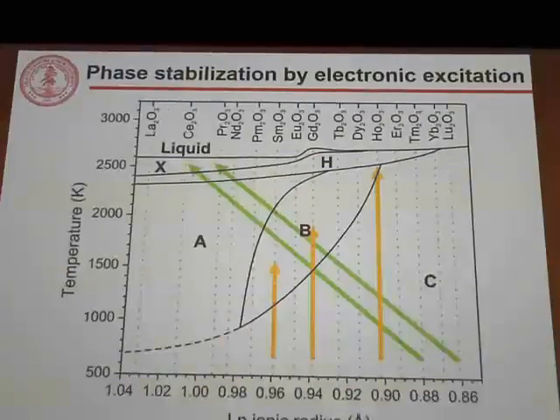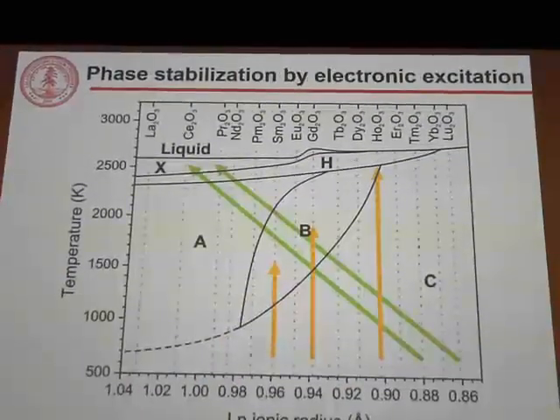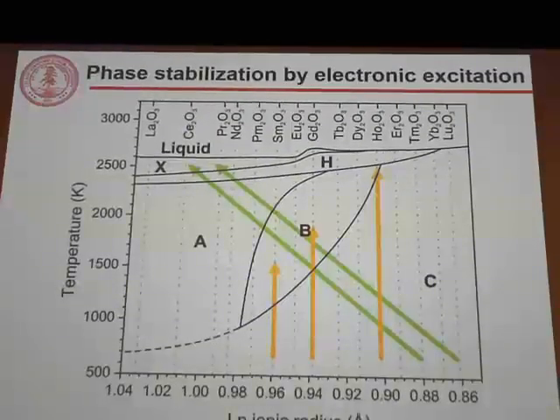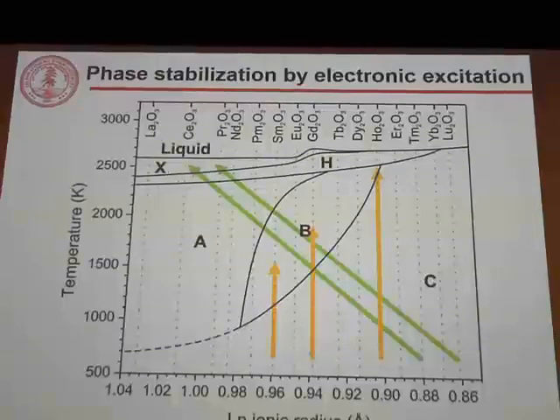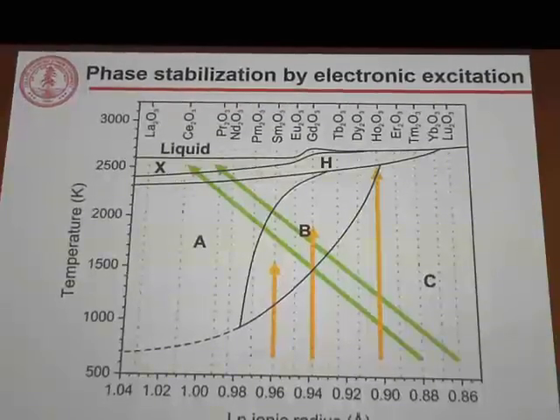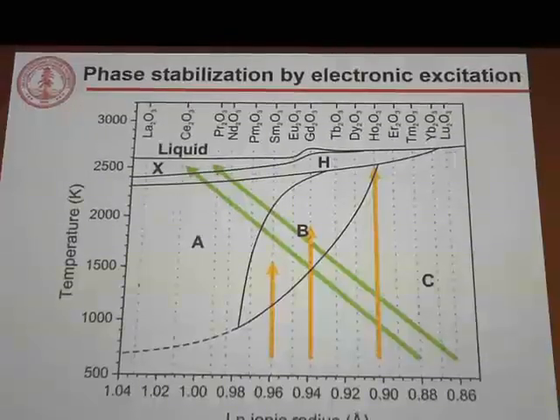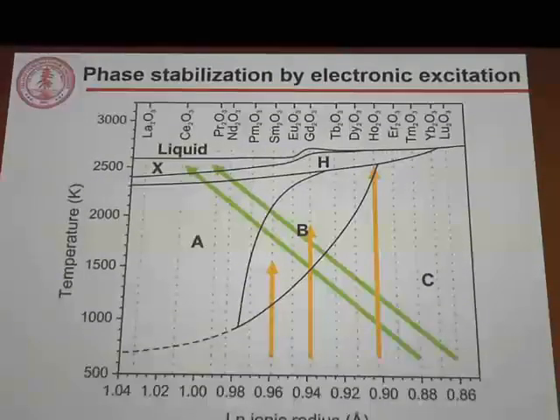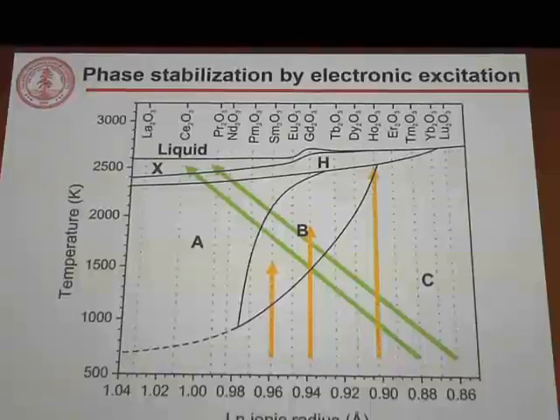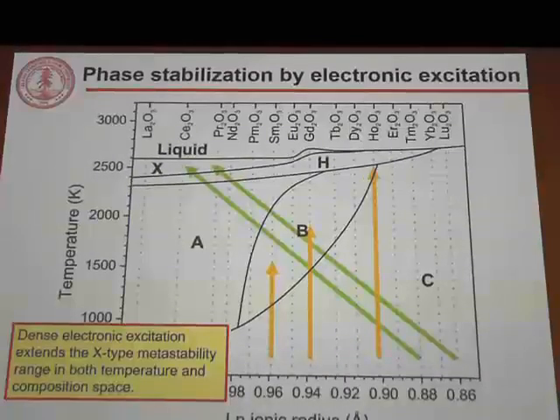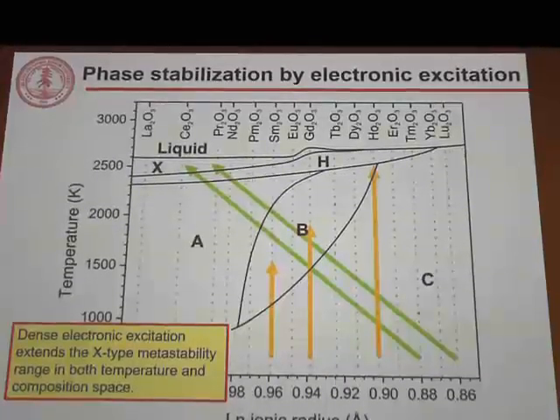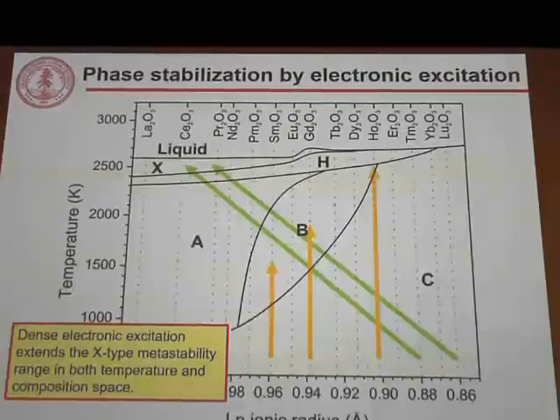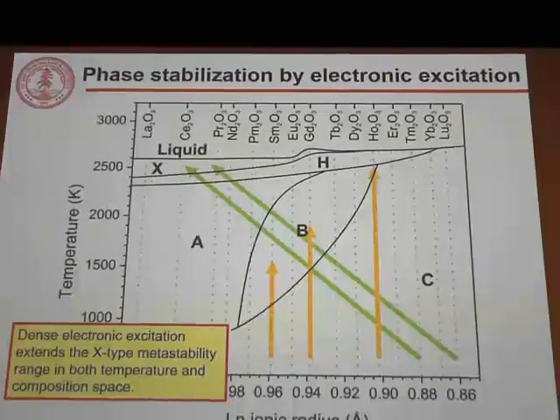Now this is really interesting because we're stabilizing this X-type phase not only for the first time to ambient pressure by making it through irradiation, such that it is metastable after irradiation, but we're also extending its metastability range in composition space. You see from this phase space diagram that it forms only up to holmium sesquioxide. However, we've formed it for thulium and lutetium sesquioxides, so we've extended not only the temperature range of metastability, but the composition space.